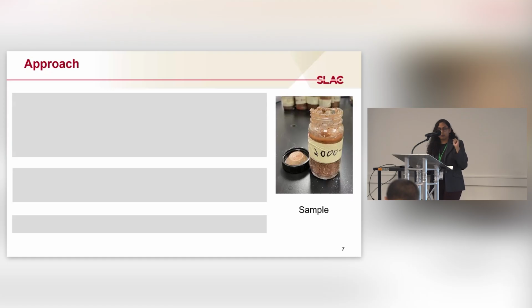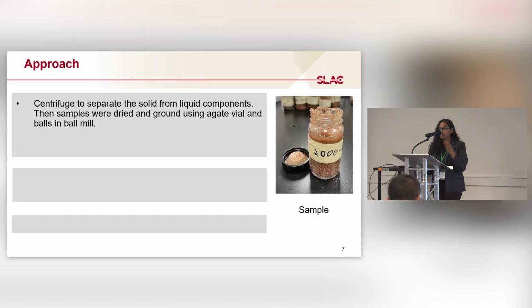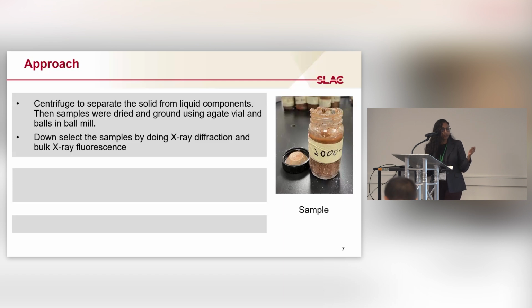First, these materials were centrifuged and separated, ground and dried. All of these samples were pre-screened using XRD and XRF: X-ray diffraction, or XRD, for understanding the mineral composition, and bulk X-ray fluorescence measurements for getting the general elemental composition in these materials. Once we got the elements and mineralogy of these samples, we down-selected which samples we were interested in.